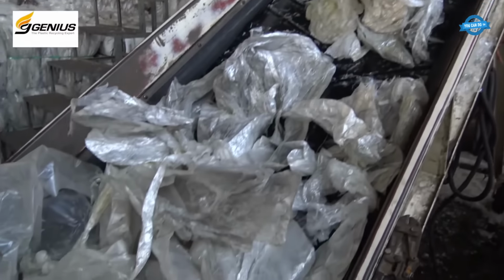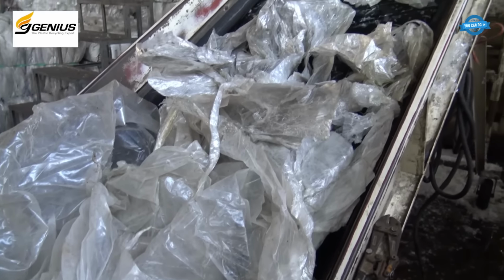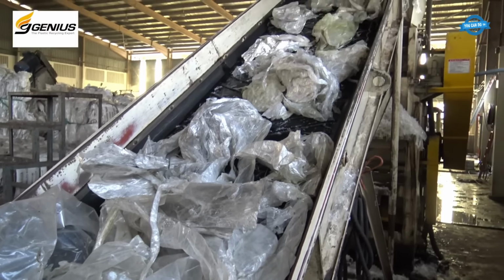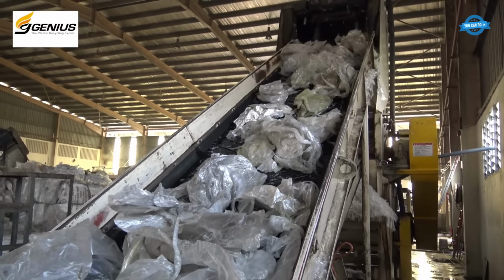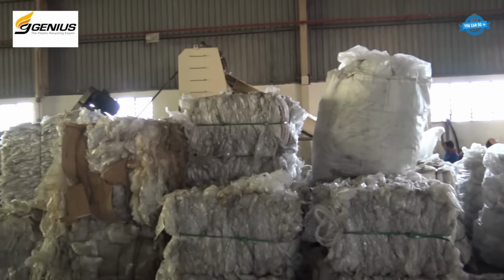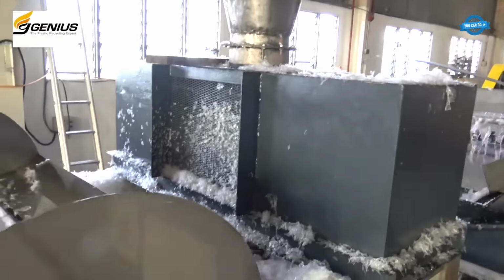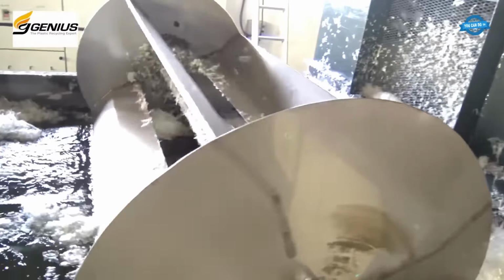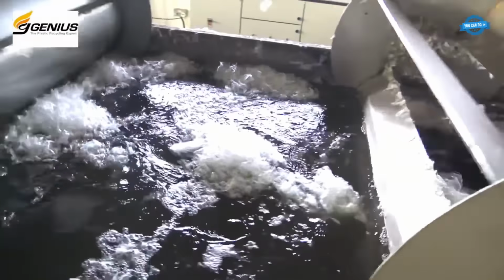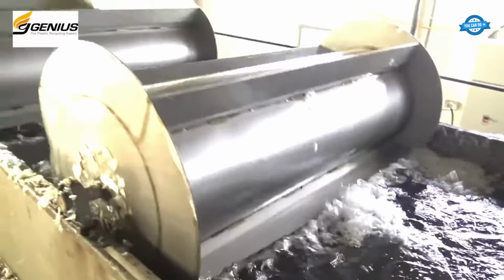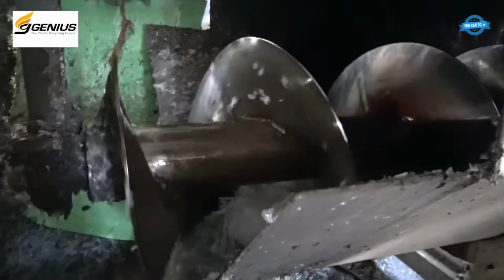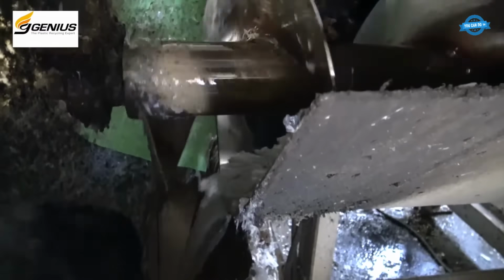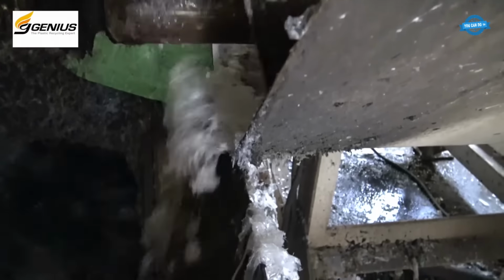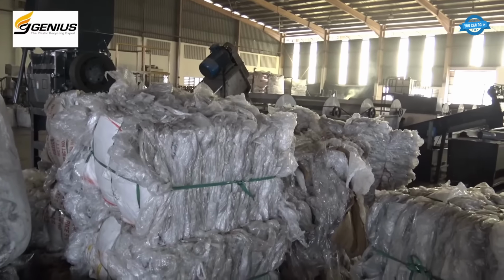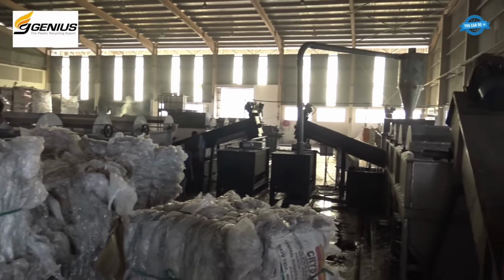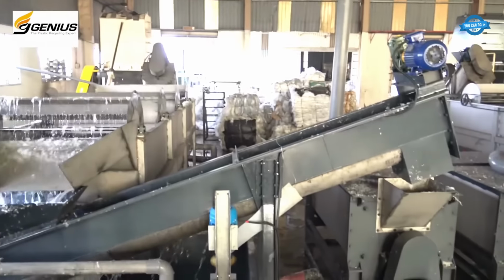Washing ocean plastic is not comparable to rinsing a bottle collected from a curbside bin. Every grain of salt left behind becomes a threat to the machinery downstream. Film washing systems for LLDPE and LDPE show how aggressively contaminated plastic must be treated before it can re-enter production. Agricultural films and post-consumer sheets arrive mixed with dirt, moisture, and organic residue. Washing lines shred the material, separate contaminants, squeeze excess water, and reduce moisture content before extrusion.